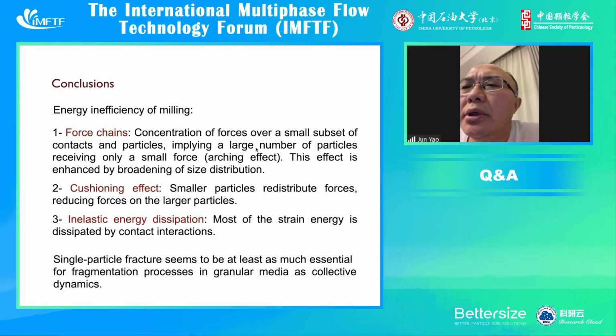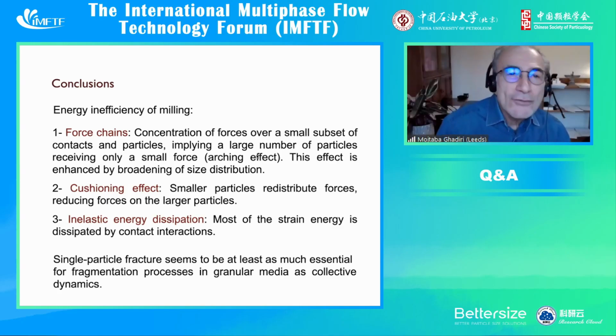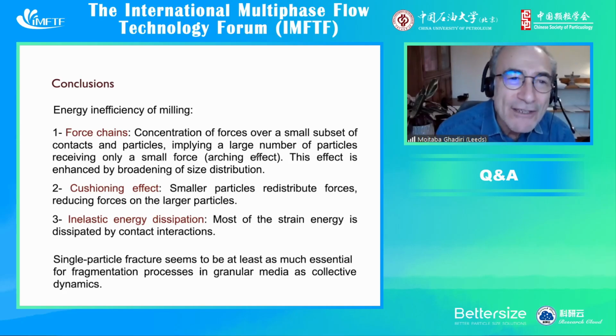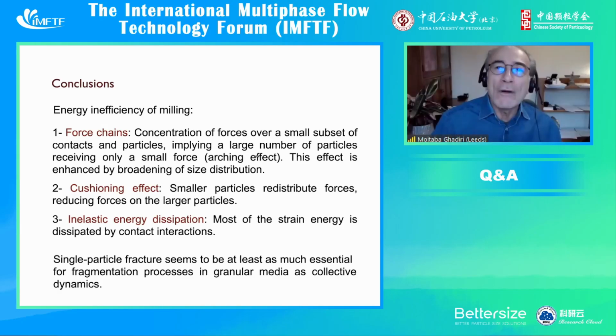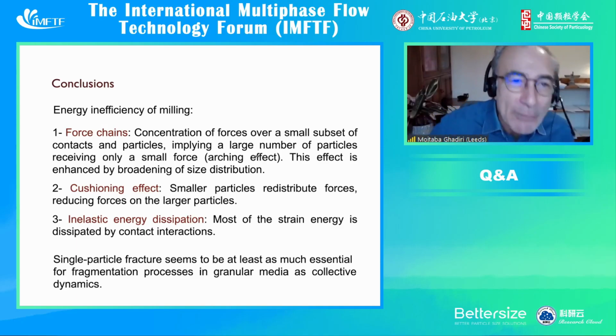Okay. And another question from the gallery says that the new vertical roller mills reduce the cushioning effects. Yeah, I should comment on that. The point of cushioning reducing the efficiency of milling is really a big problem. For example, drum mills are very prone to that. A company in Newcastle in England developed a vertical roller mill where the rollers were rolling on a vertical wall, and when the particles were crushed, they were separating the fines.